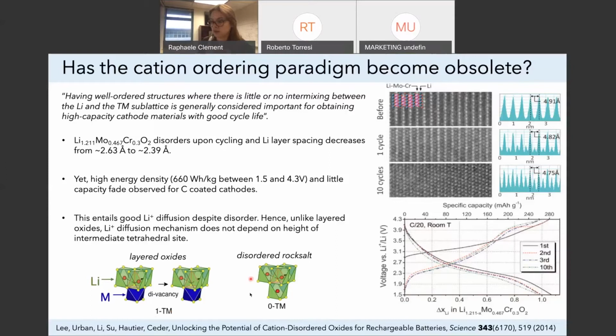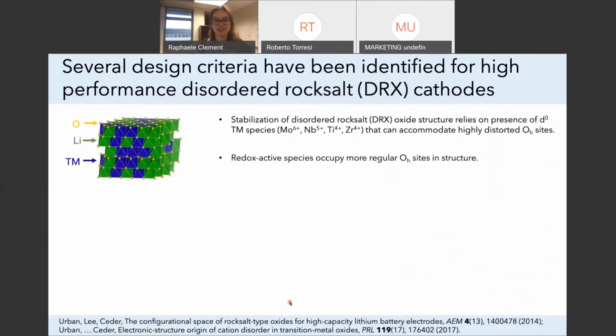And so these we call zero transition metal channels, and it is believed that these types of local environments or channels are the ones that allow fast lithium diffusion in these cation disordered compounds. So we need to rethink a little bit how we visualize diffusion in these materials.